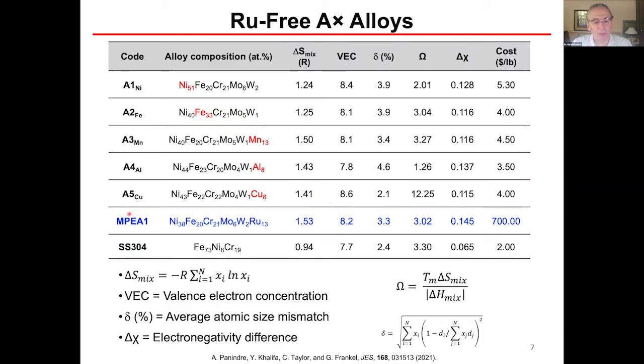All right, so again, with our starting composition of MPEA1, which has nickel, iron, chromium, a fair amount of molybdenum, a bit of tungsten, and then this ruthenium, which has the very high cost. We've developed these 5 different alloys. We call them A1 through A5, and then with the subscript of the element that is replacing the ruthenium, just to remind you of that. Okay, so you see that these alloys aren't exactly this MPEA1 with ruthenium exactly replaced by these elements, but with some tweaking to allow this wide range of solid solution expected at higher temperatures, we've ended up with these alloys.